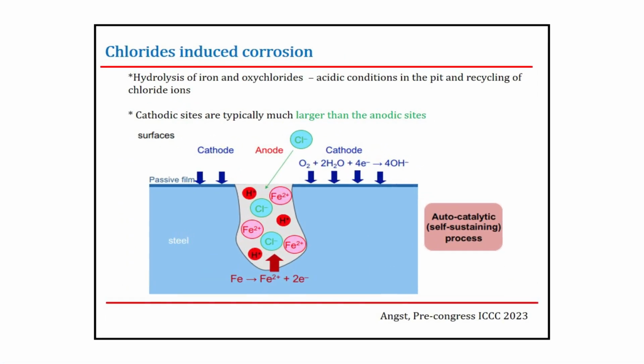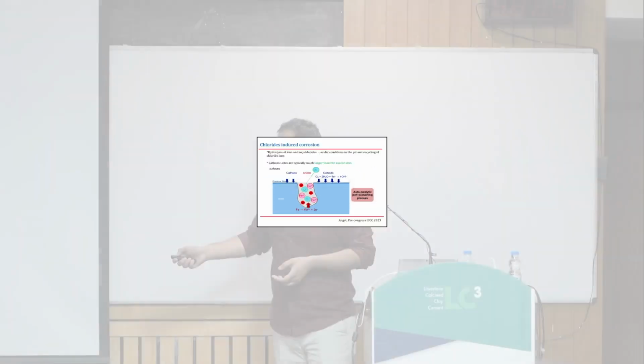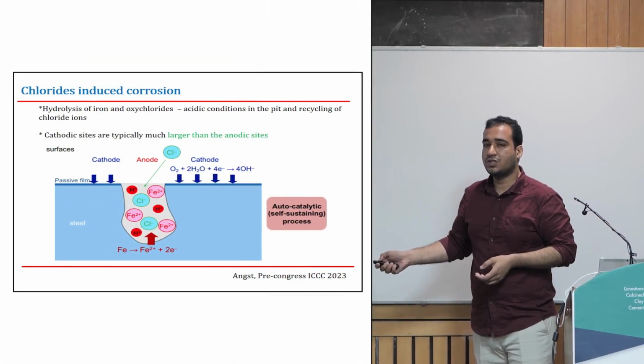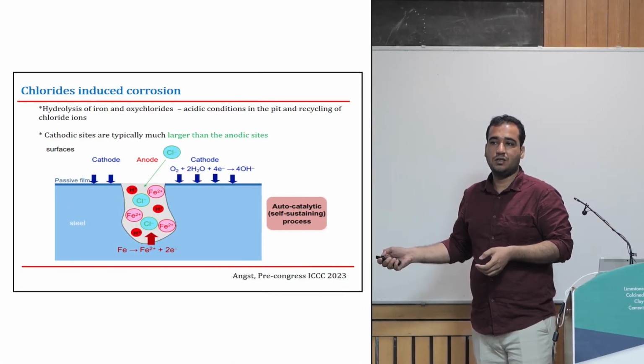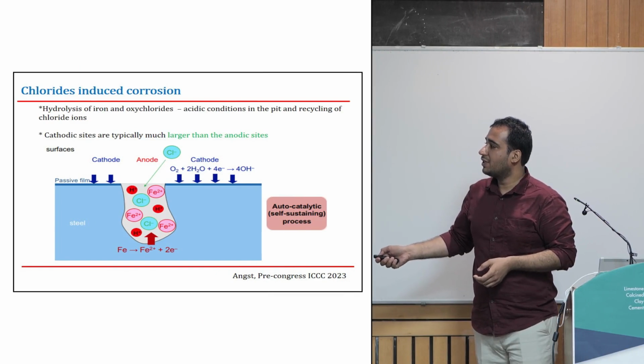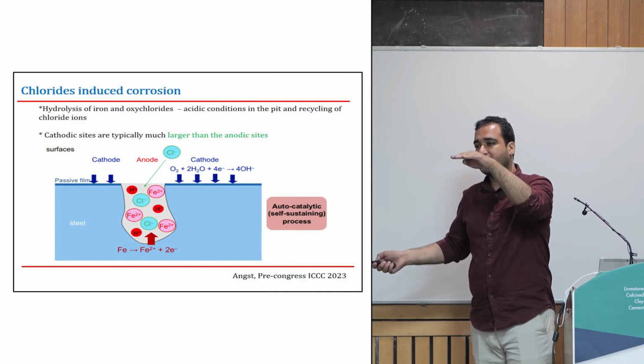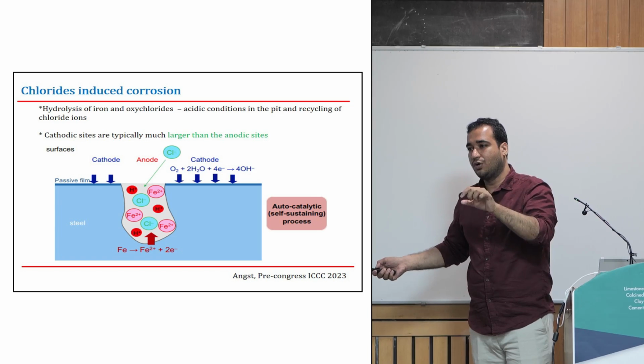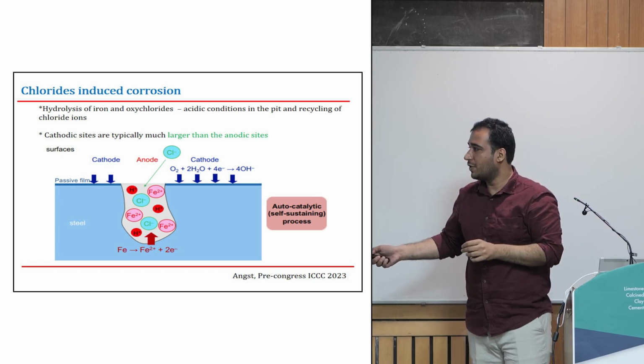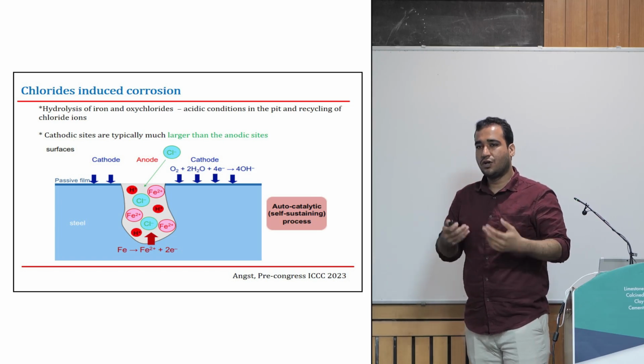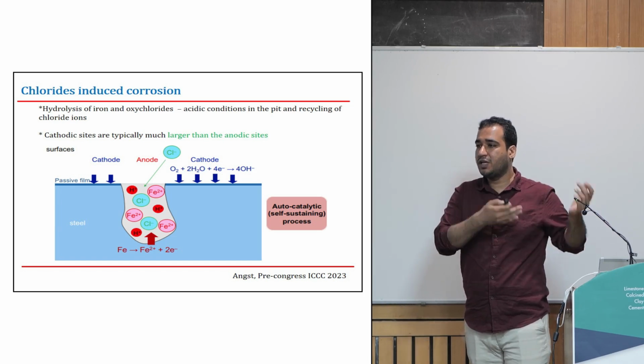To be more specific, when this iron starts dissolving, it forms oxychlorides and they start hydrolyzing. In this hydrolyzing process, hydrogen ions are released, and locally inside the pit you start having an acidic environment. This acidic environment brings down the pH inside that pit only, not of the whole concrete but inside the pit.